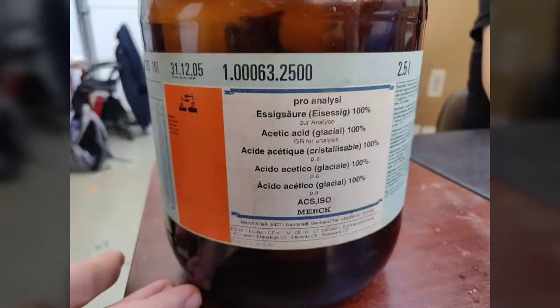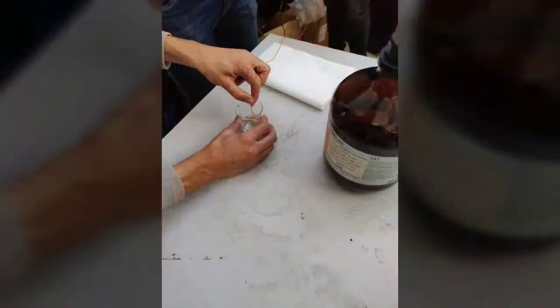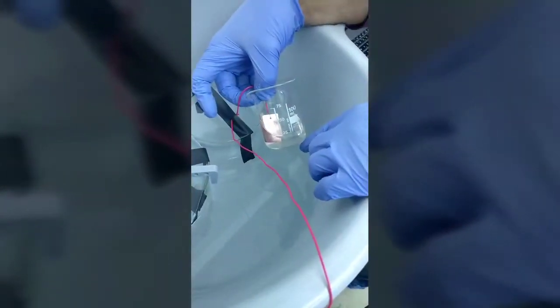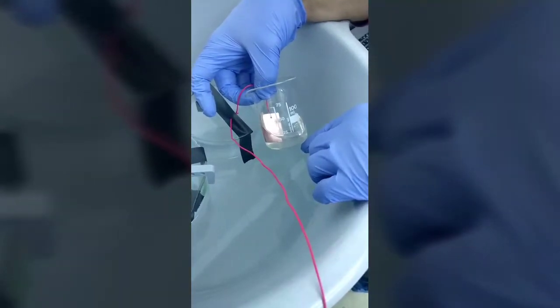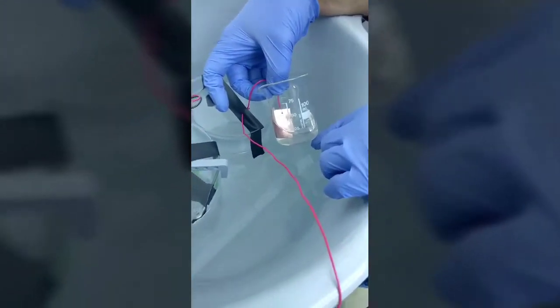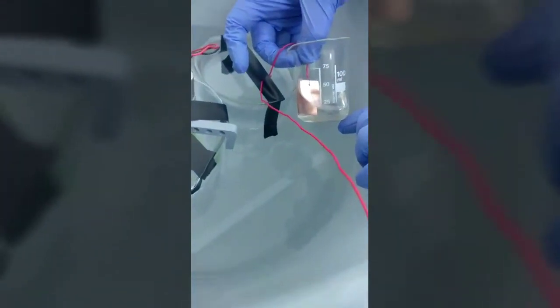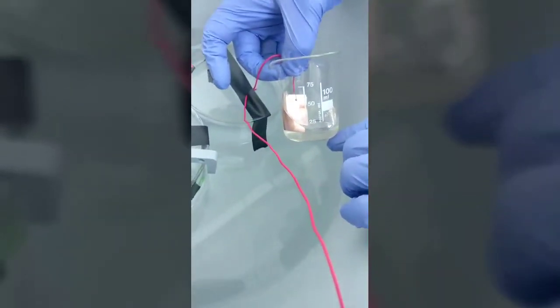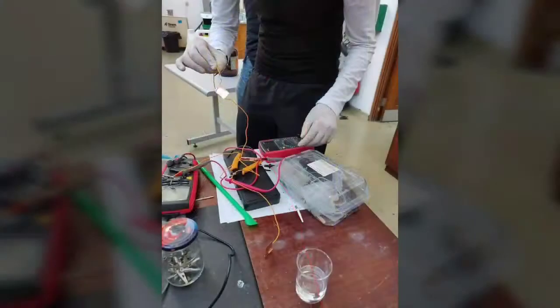The copper electrodes, on the other hand, were first submerged in concentrated acetic acid solution, so as to expose the parent metal underneath the oxide layer. This, however, was not followed by rinsing with deionized water, because doing so would reoxidize the copper and also form cupric hydroxide. The electrodes were then dabbed with clean cloths to remove excess acetic acid. This was done in less than 1 minute, so as to preserve the free oxide surface required.